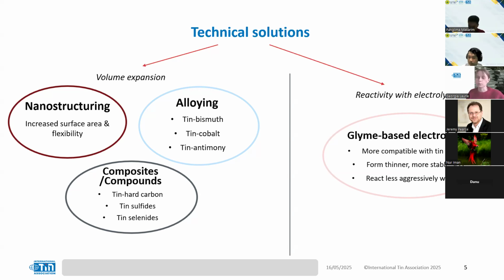Additionally, we can alloy tin with other metals, or we can form composites with materials like carbon, for example. These materials can help to buffer the volume expansion by, again, increasing flexibility and also absorbing some of that expansion. If we look at tin hard carbon, for example, these composites can use porous carbon materials, which essentially has holes in it for tin, which not only makes it more flexible, but also creates a matrix that can hold tin in position.